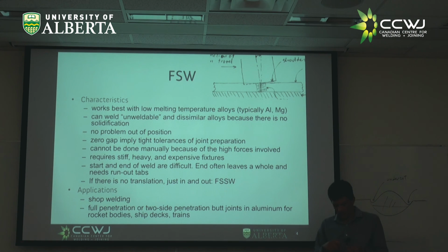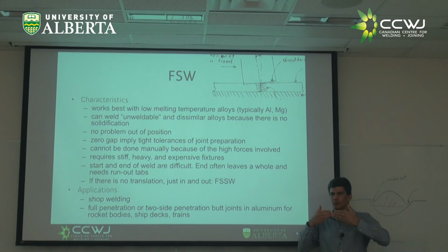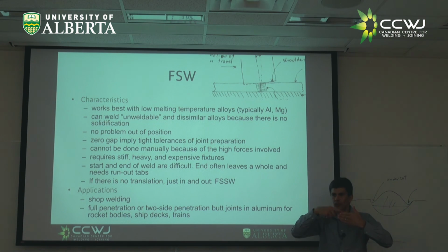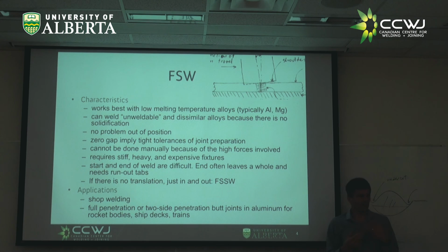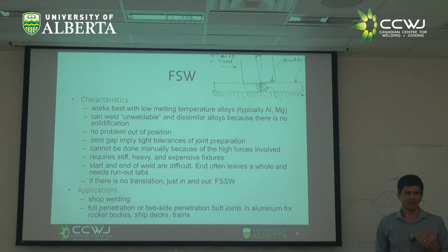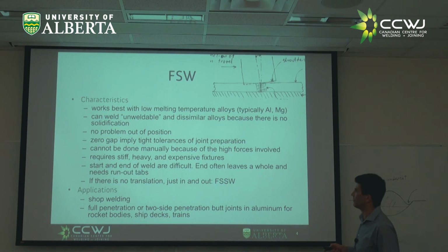It's also, as I was talking about the stirring, you realize that you cannot have a gap. If you have too big of a gap, as you stir the material, you're going to create a mess with porosity because you're missing metal there. It's autogenous. In autogenous welding, you typically want no gap. Because if you have a gap, guess what? There is no filler to make up for it.